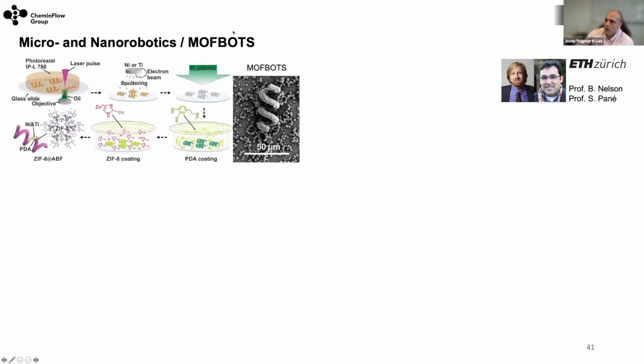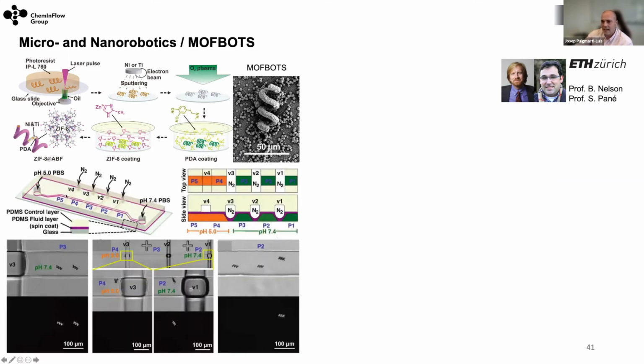So we wrote a project together with Salvador that was funded via ETH. And the idea was this one here. We have the helix that the group of Professor Brad Nelson developed some years ago. And what we decided to do here was to equip these helixes with MOF crystals. So we need a microfluidic device that enables us to have two different pHs: pH 7, where the ZIF crystals will be more or less happy, and a pH of 5, where the ZIF crystals will dissolve. And what we did was to encapsulate rhodamine in the ZIF crystals.